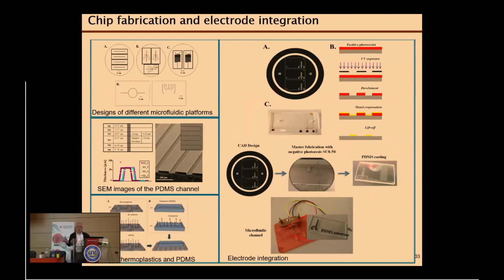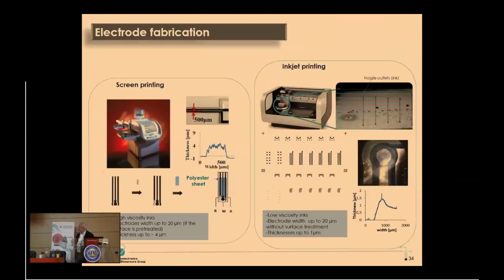This is one case using PDMS. And also we are able to integrate electrodes inside these channels. And you see why we do this. If you want to detect in this sample, sometimes you need to run the sample and pre-concentrate on top of the electrodes. And this is why we print electrodes. We have screen printing technology. We use inkjet printing, which are very interesting techniques.